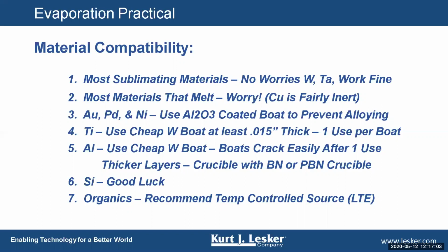Titanium, a common material done in resistive thermal evaporation. I tend to only use cheap tungsten boats that are at least 15 thousandths of an inch thick. And you can almost guarantee that with titanium, you're only going to get one use per boat because it is going to dissolve, interact with, and pretty much destroy the boat after one use. And generally the layer thickness after that one use, if you're shooting for 100 or 200 nanometers, should be okay, but anything much more than that, it's not going to work for titanium.